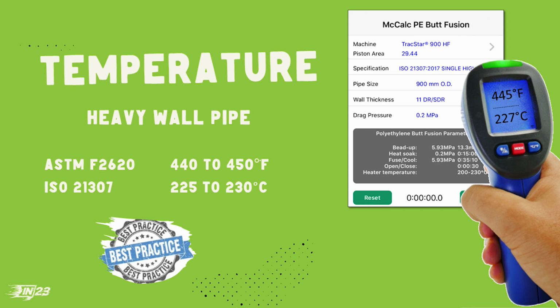The other aspect is that after you've heated it, you've got your melt and everything's right, you're ready to open and close, a larger diameter heater plate takes longer to get out. If you're starting off at 415, by the time you get it out it could be 380, I'm just making this up. But if you're at 450 and it drops 20 degrees, now you're at 425, where you want to be. So part of the heat is making it robust so that you maintain your heat. Good point, thanks.